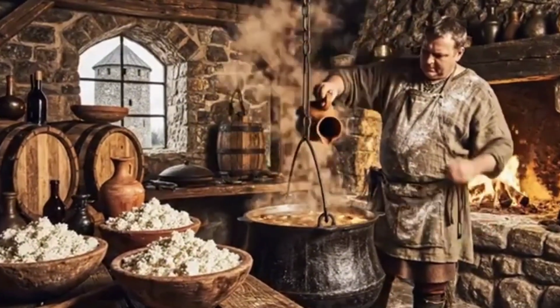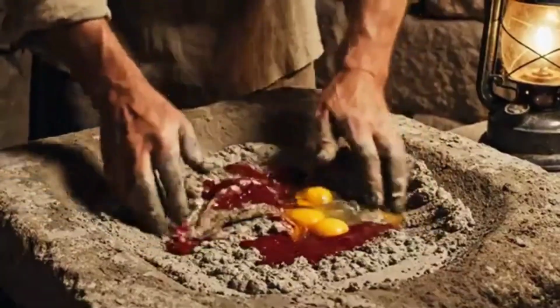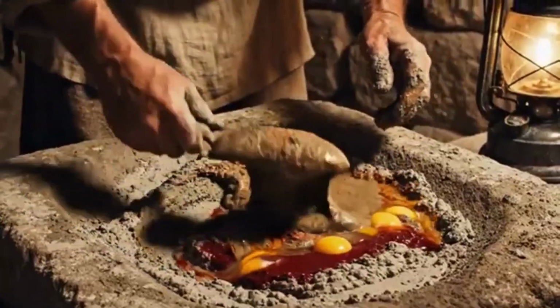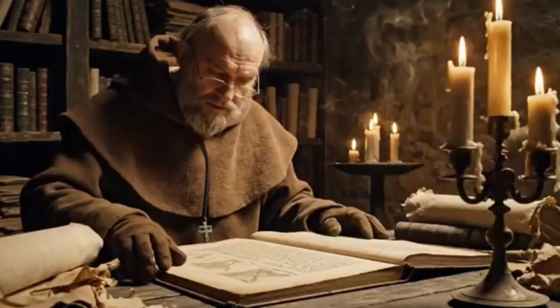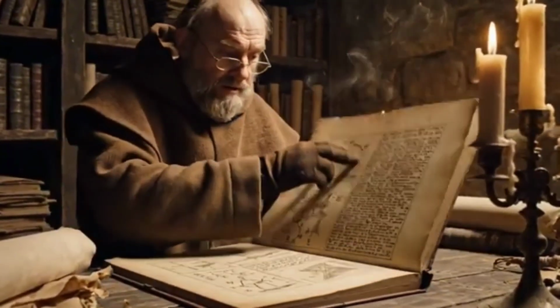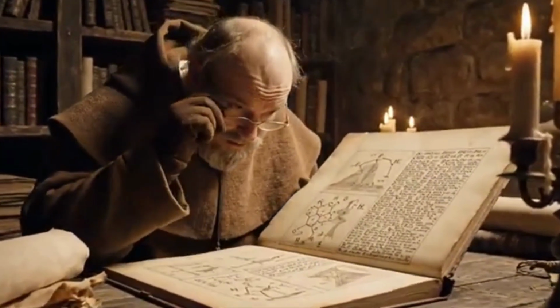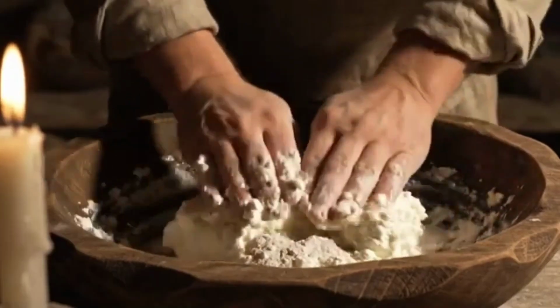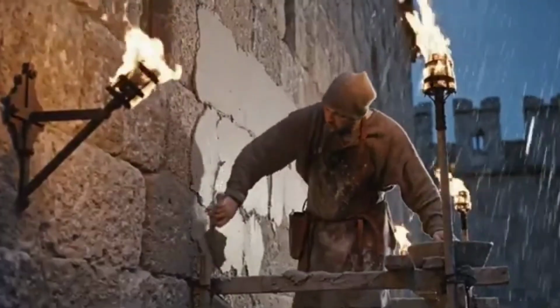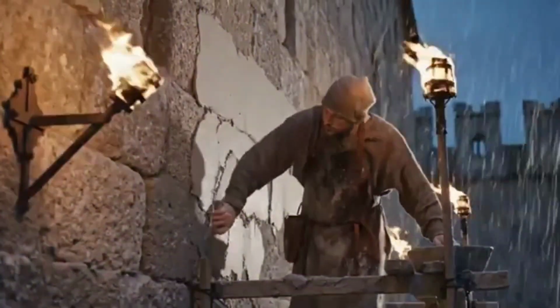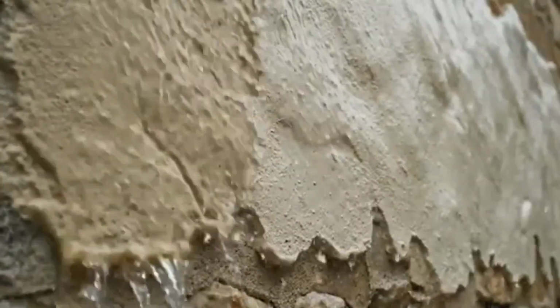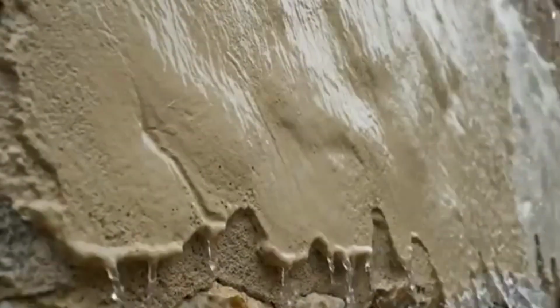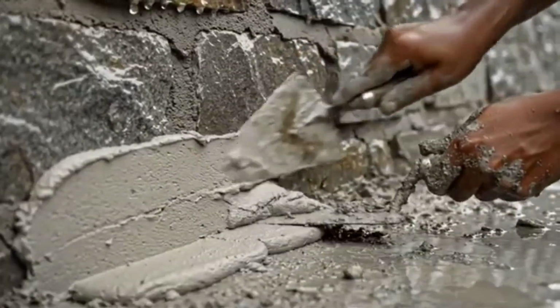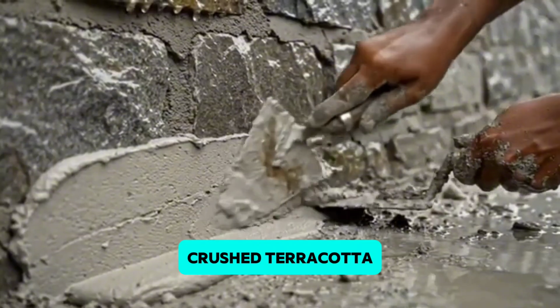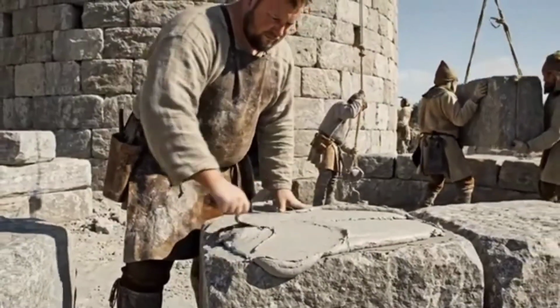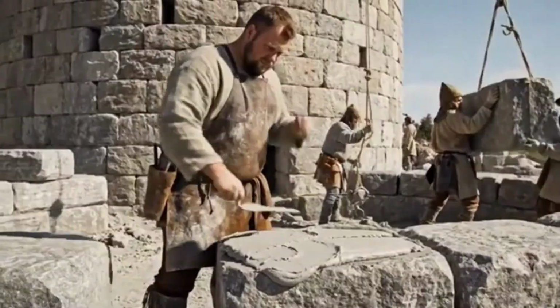In 476 AD, the Western Roman Empire collapsed, and with it, the large-scale production of pozzolanic concrete largely disappeared from Europe. But here's what most people get wrong about this. Medieval builders didn't lose the ability to make durable structures. They lost access to the specific volcanic resources and the centralized logistics networks required to transport pozzolana across the continent, so they adapted. Medieval construction shifted towards slaked lime combined with local sand and crushed aggregate. In the absence of volcanic ash, some builders used crushed terracotta, called testa tunsum, or plant ash as pozzolanic substitutes to give their mortars hydraulic properties.